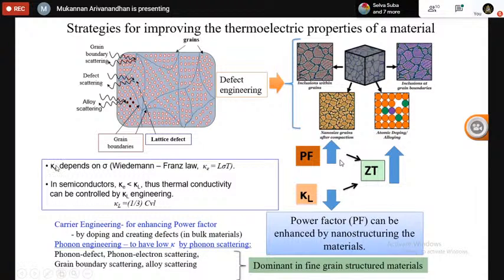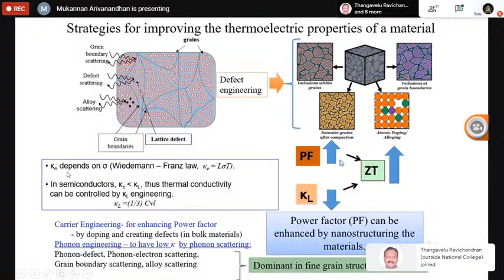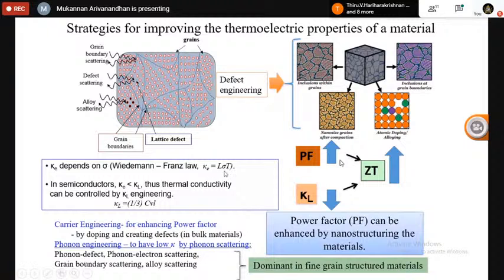As I said before, the electronic part of thermal conductivity is directly proportional to the electrical conductivity according to the Wiedemann-Franz law. Whereas in semiconductor-based material, the lattice part of thermal conductivity is dominant, right? So how is the lattice part of thermal conductivity changing based on the material? Here you can see the relation. The lattice part of thermal conductivity is a function of three parameters: the specific heat capacity, the phonon velocity, and the phonon mean free path. So you can play with this phonon mean free path by creating these kinds of defects.